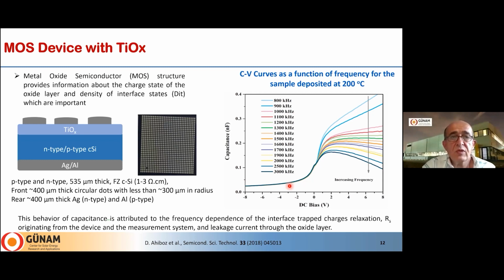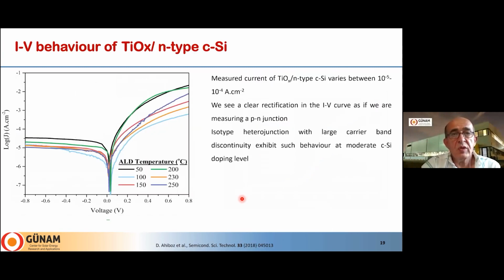So the reaction of these charges depends very much on the frequency of the measurement that you use during the CV measurement. So this is quite expected. The electrons are somehow stored at the interface, either at the interface states or in the bending quantum well structures. An interesting measurement was the IV measurements of these materials.